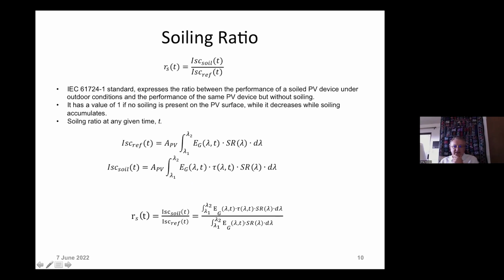The numerator has to have the transmission. You lose transmission with soiling. And so the name of the game in soiling is to try to estimate or measure the transmission, or the transmission loss due to soiling. And we call the transmission T, tau. So again, if I form this ratio from these integrals, it's the reference in the denominator and a similar integral which has the transmission in the numerator. So we want to measure this transmission as a function of wavelength at a particular time T, because it's changing. Tomorrow you may have a dust storm in the desert, and so time T1 might not be time T2. So we have to specify that.